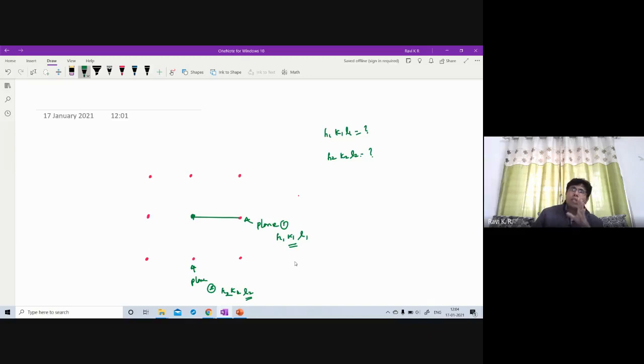First thing, when you do all this calculation, whenever you have an image, you should not stretch it. Stretch means you should not stretch in the x direction or y direction, because what we are going to do is what we call a ratio method. So when you stretch in one side, in the x direction or y direction, this is going to be a problem. You should not stretch it. You can make it bigger, but without affecting the aspect ratio. That is a very important thing that you need to remember.